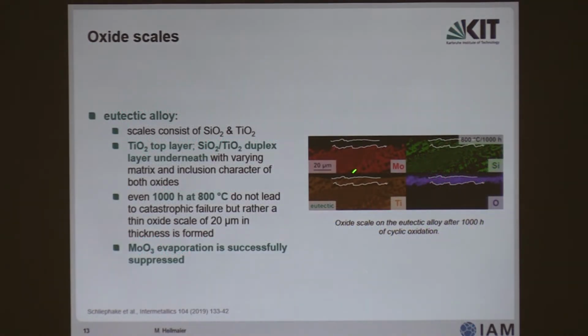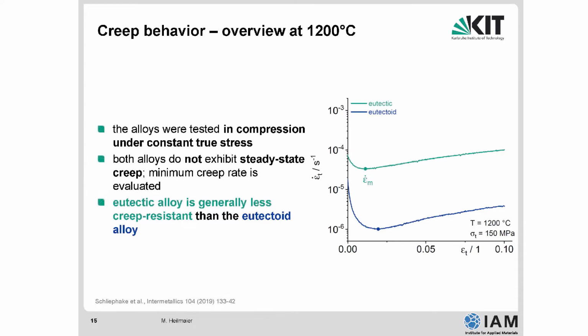Of course, you can also look at the 800 degrees Celsius oxide scale. It shows, again, protectiveness by forming these duplex scale layers. I don't want to go too much into detail. If you have any questions, I would be happy to answer them afterwards. Let me show you instead the creep behavior for these two alloys. And now, as always, a metal has two sides, right? On one side, it's shiny. On the other side, it's not so nice. The drawback of this eutectic alloy comes with the creep behavior.